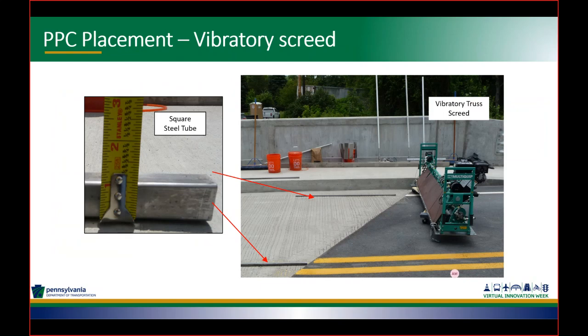About the placement, if you have a smaller job or a thinner lift, like an inch, up to 2 inches, I would say, you can use a vibratory screed. You can place steel tubes inside just to get the height that you're looking for. And not much different than you would be placing a cementitious material.